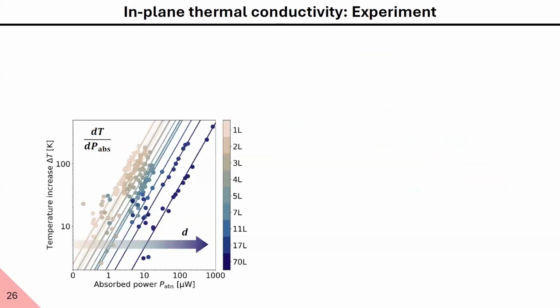So let's plot the temperature increase at the center of our suspended region as a function of laser absorbed power. We see that our thinner samples are on the left side, while our thicker samples are on the right side. So they are very well sorted by thickness. This is a very intuitive result. A thicker material needs a higher absorbed power to increase the temperature to the same level as a thinner material. This is basically because we have a larger volume in which heat spreads, and therefore we need more power to heat it up to the same temperature.